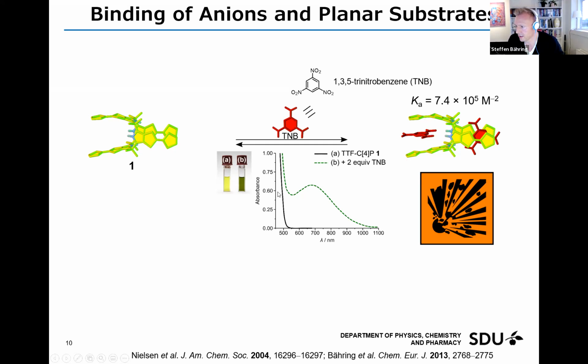And this can be seen here in a colorimetric response, where we have the yellow compound for the calix[4]pyrrole, and then TNB, which is colorless, upon addition, turns the solution green. And you can see this band here, which is quite strong, from the charge transfer. And this is estimated to have a binding affinity of 10 to the 5th. So this is quite strong. This was, of course, very interesting because being able to detect or bind explosives is of interest to everyone.